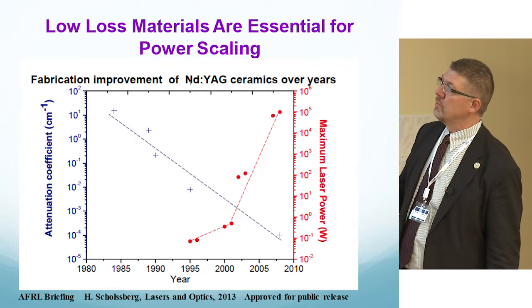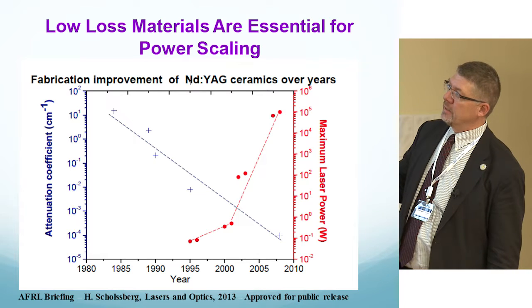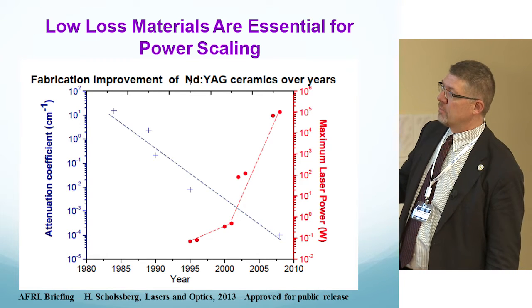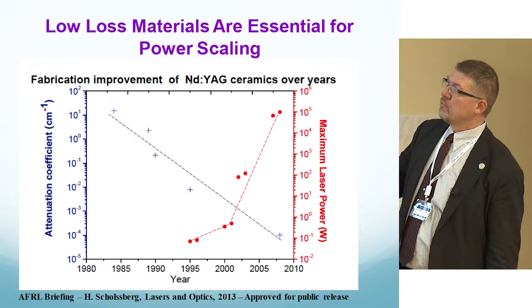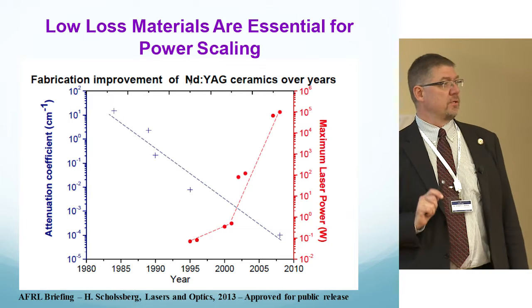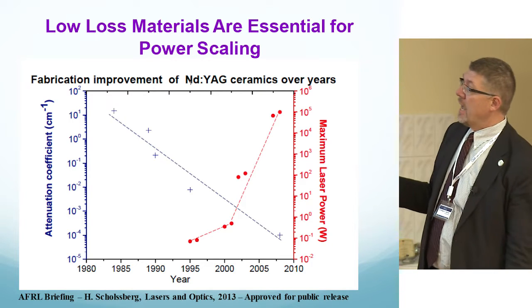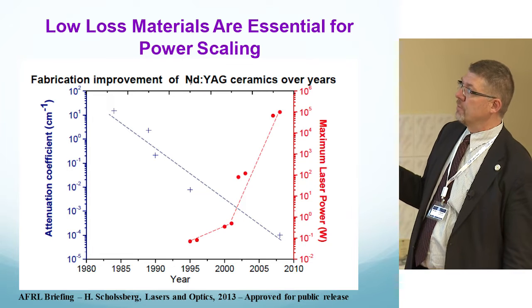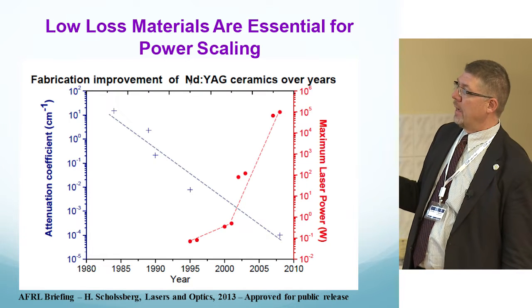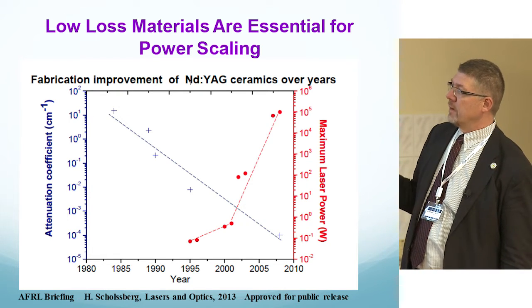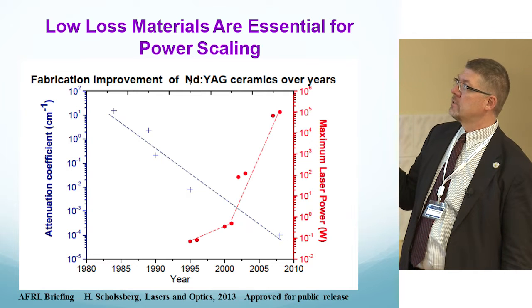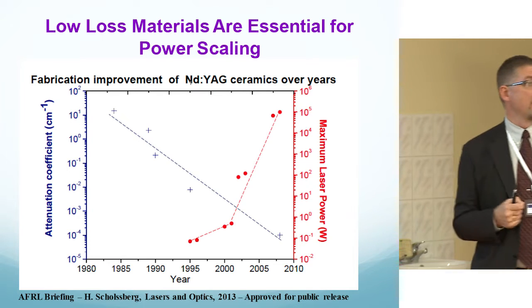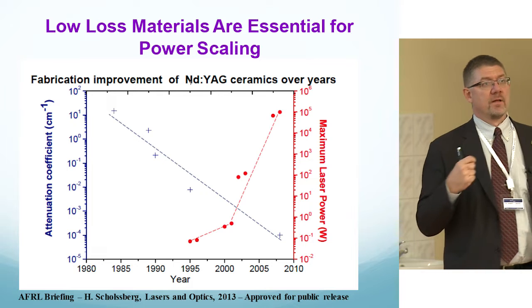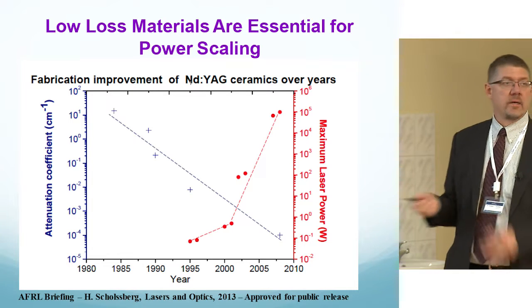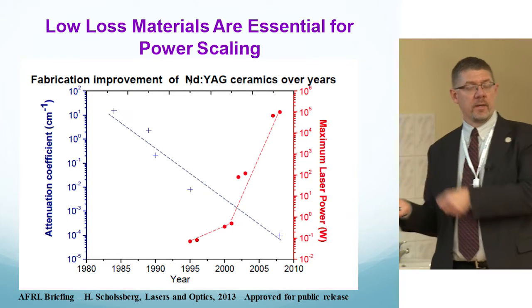And what this chart shows is losses starting in 1985 down to almost 2010, dropping by almost four orders of magnitude. And the laser output power from these samples of neodymium YAG going from down here at 10 milliwatts up to 10 to the fifth watts. So these two go hand in hand in driving the ability to generate high levels of output power out of a crystal.